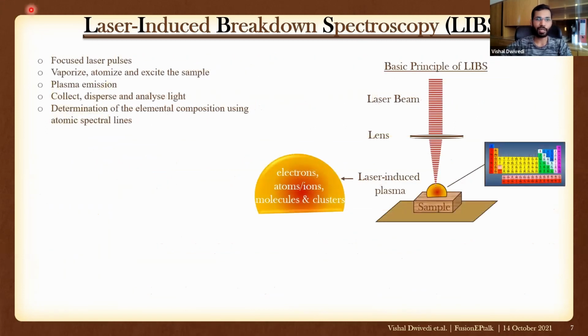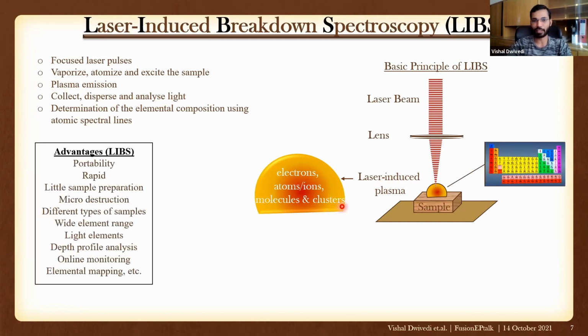So in short, we have a focused laser pulse, and when it is focused on the sample surface using the lens, it vaporizes, atomizes, and excites the sample and creates the plasma emission. This plasma emission we can collect, disperse, and analyze, and from that we can determine the elemental composition using atomic spectral lines. Almost all elements from the periodic table can be determined using LIBS. And this laser-induced plasma contains electrons, atoms, ions, molecules, and clusters.